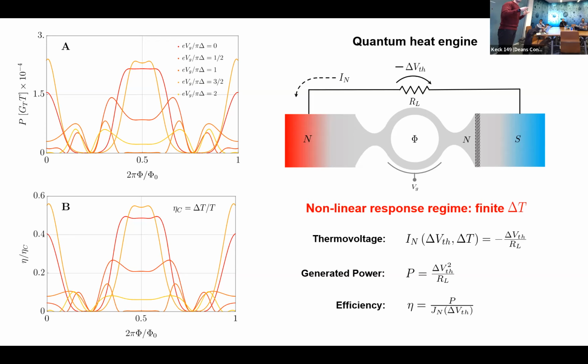And this is much better than the case in which you substitute, for example, the superconducting lead with a metallic one. The fact that we can obtain such high values of the efficiency is because of the presence of the superconductor, and more precisely because of the Andreev reflection processes that happen at the interface with the superconductor. Whenever an Andreev reflection takes place, an electron with energy epsilon is reflected back as a hole with the same energy. The superconductor is acting as a kind of mirror for energy flux, meaning that it blocks the flux of heat current through it. Because the heat current gets smaller and it appears in the denominator of the efficiency, the efficiency gets higher with respect to the case of a normal metallic lead.